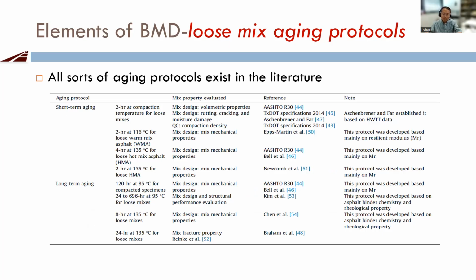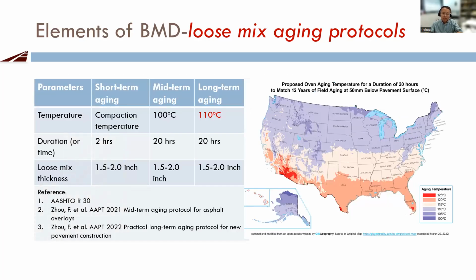In the literature, I have all sorts of aging protocols, and you can see multiple protocols, but which one can be practically used? So that's how we studied different aging protocols. We published several papers, two papers in the AAPT conference 2021 to 2022, talking about the midterm aging for overlays, and another on long-term aging for new pavement construction. Basically, this is what we recommend for short-term aging: the temperature is the compaction temperature, and the duration for aging loose mix in the oven is 2 hours. How thick the loose mix is: 1.5 to 2 inches. You really don't want it too thin or too thick. So that's what we recommend for short-term aging.